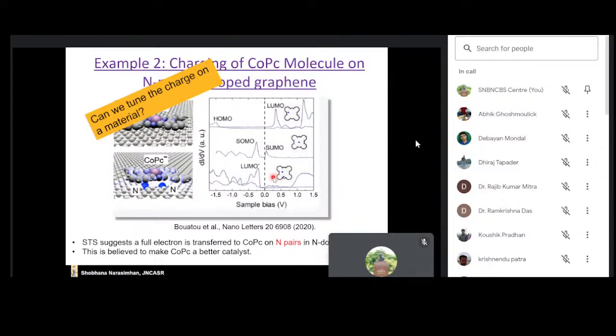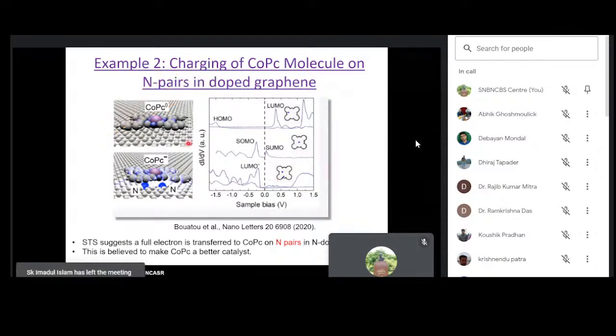Now let me come to the next example, which is whether we can tune the charge on a material. So this flat molecule is cobalt phthalocyanine, and it is deposited on graphene, which has been doped with nitrogen atoms. Now, if this molecule is sitting on either undoped graphene, it is a neutral molecule. If it sits on a single nitrogen dopant, it acquires a slight negative charge. But if it sits on a nitrogen pair, that is, if there are 2 nitrogen atoms underneath the cobalt phthalocyanine molecule, it acquires a full unit of negative charge, that is 1 full electron.